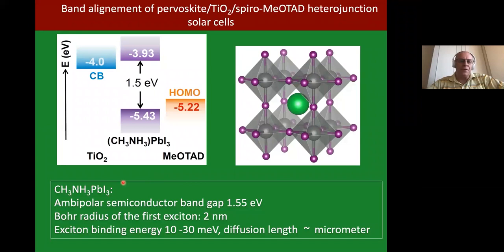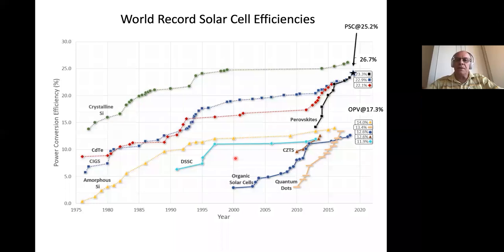And methylammonium lead iodide has a good band gap for a solar cell, 1.55. When you excite electron-hole pairs, they easily dissociate. So it doesn't take much exciton binding energy, they dissociate. And the lifetime of them is long enough that the charge can diffuse to the contacts, electrons to the negative and holes to the positive. So it's an ideal semiconductor in that sense. And moreover, it can be produced in your chemistry lab. So you can do it by solution processing, which is a really amazing observation.